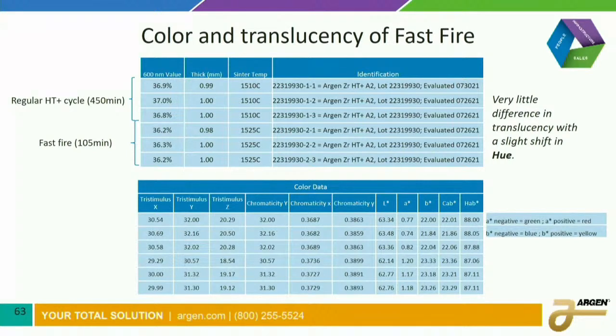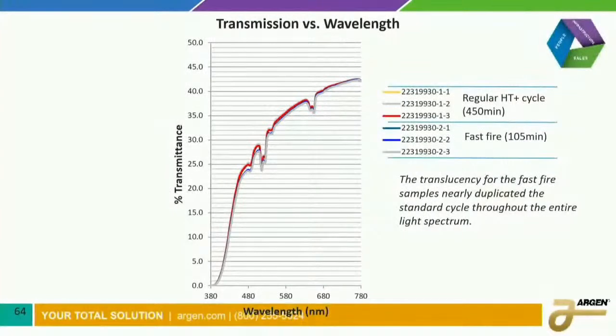Here's 450 minutes, here's 100 minutes, a fourth of that, and you develop it pretty well. And you see on the color itself, the hue is a little different. We go from like 88 to 87. So we did a slight difference in hue, but it came out with the shade close to the shade guide. Okay.